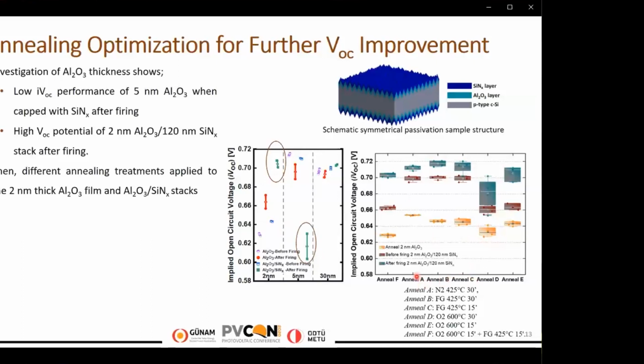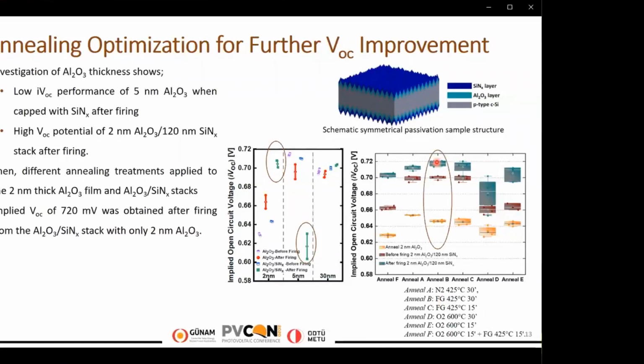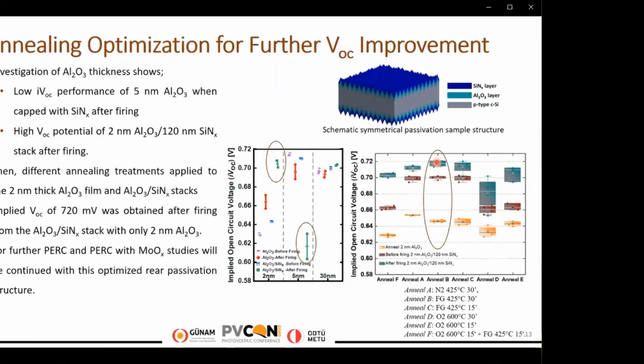Different annealing treatments apply to 2 nanometer thick aluminum oxide film and aluminum oxide silicon nitride stacks. And for 2 nanometer aluminum oxide, a forming gas anneal at 425 degrees for 30 minutes seems more advantageous in terms of VOC, reaching implied VOC of 720 millivolts here. So for further PERC and PERC with molybdenum oxide studies, this stack with this annealing will be employed in order to reach higher cell VOC levels.